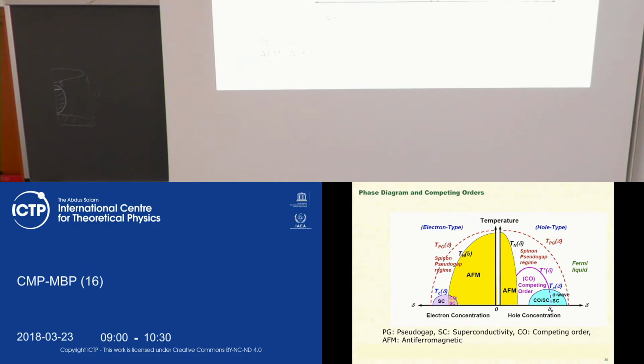Again, summarizing, these high temperature superconductors, which are based on copper oxide, are quasi two-dimensional materials. These are electron systems with initially quasi-localized orbitals. Therefore, some strongly correlated models like the Hubbard model are highly likely to be responsible for the superconducting property. So, two-dimensional strong correlation. The symmetry of the order parameter is not spherically symmetric. It's d-wave. And moreover, the superconductivity develops as a matter of competition between different strongly correlated phases, such as the antiferromagnetic phase and the superconducting phase. So it looks like the high temperature superconductivity is driven by this competition. This is a compromise which the system finds.